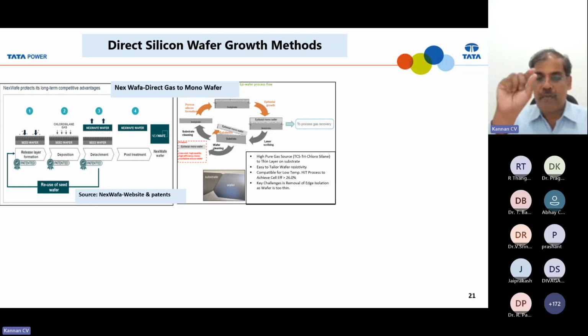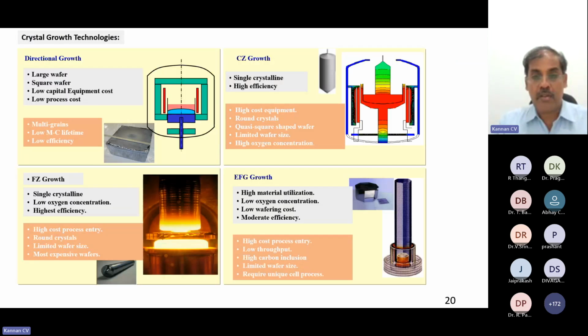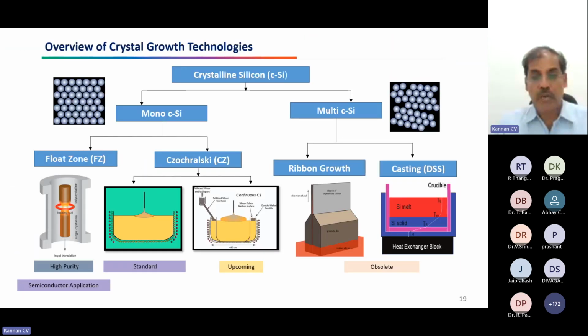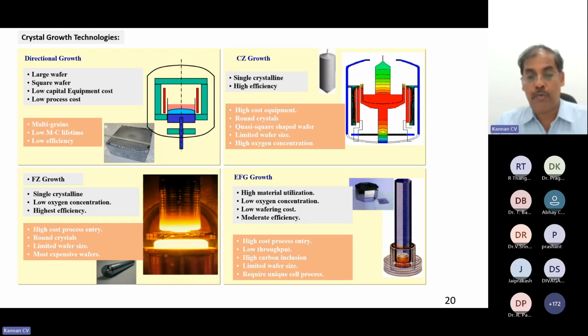But unfortunately, that wafer thickness will be very, very small through the gaseous phase. You cannot grow even micron level. It will be nanometer level, or maybe 1 micron, sorry, 10 micron, 20 micron, 30 micron, that level. You cannot grow 200, 300 micron. Whereas in the previous cases, you can grow even 300 micron, 400 micron, 200, whatever thickness you want. You can design what thickness you want, what shape you want. So a lot of flexibility there.